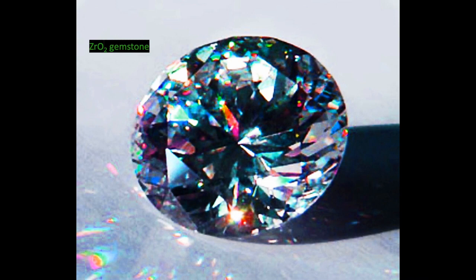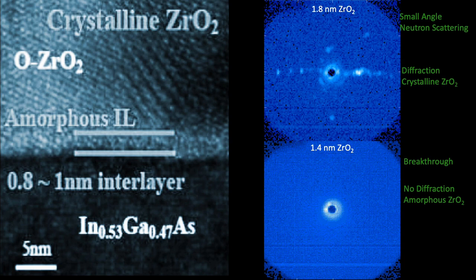Zirconium oxide is an incredibly tough and resilient component of grinding wheels, sandpaper, and other abrasives. In cubic crystal form, it is cut into gemstones to compete with diamonds — optically flawless and usually colorless. The silicon substrate was replaced by indium gallium arsenide, but still scavenged oxygen away from the zirconium oxide, adding an unwanted oxide layer between the substrate and the zirconium oxide. We scaled the zirconium oxide down to about six atoms thick and used small-angle neutron scattering to look for events at very slight angles of diffraction — only a few places in the world capable of making this measurement. We had high fives all around because we were finally able to circumvent crystallization.